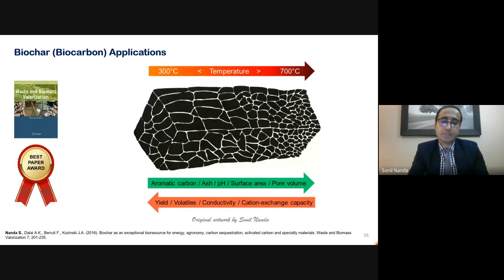Biochar has so many applications. Now, this is a paper that we published in Waste and Biomass Valorization in 2016, and it was awarded the best paper award published in that journal in that year. You can see that this is a hand-drawn image which shows the evolution of biochar as a result of the increase in temperature in pyrolysis, carbonization, torrefaction, or gasification. Now, as we increase the temperature, the aromatic carbon contained in the biochar will increase, and so will the ash content, pH value, surface area, and pore volume.